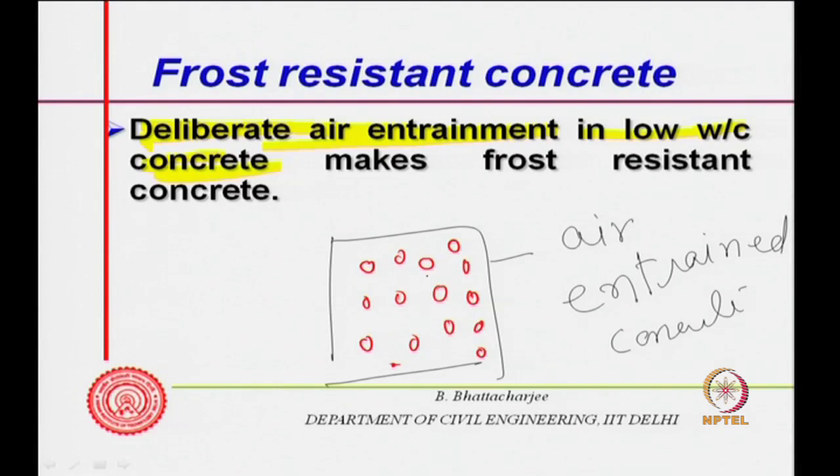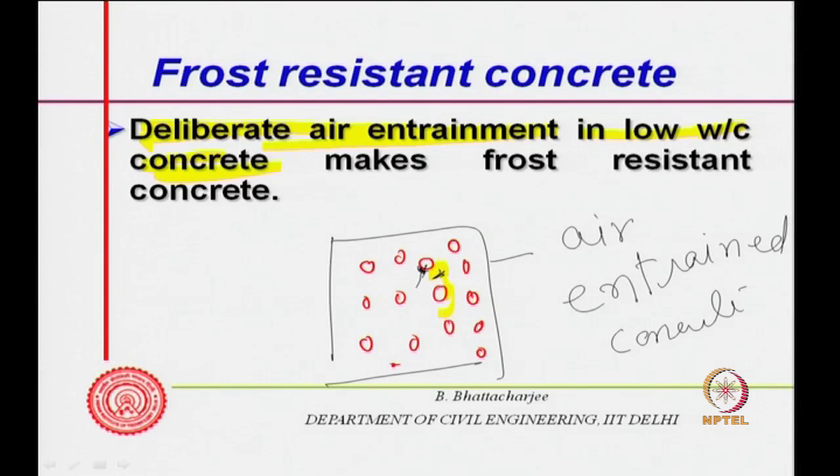Now, these pores initially are dry, not filled with water. Once the hydraulic pressure inside the capillaries increases, these pore boundaries might get ruptured and water enters there. As the water enters, pressure is released, and therefore the surrounding concrete remains intact and unaffected. So, deliberate air entrainment actually increases the freeze-thaw life.